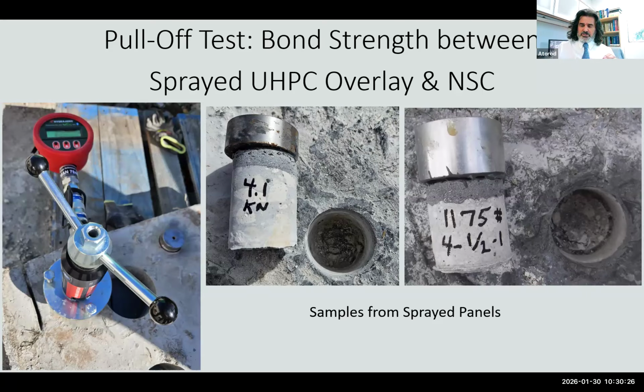If you prepare the surface correctly, and at the time of the spray or cast in place you make sure that the surface is wet, because UHPC doesn't have much water in it. The water-cementitious ratio is 0.18 to 0.2. If you don't keep the surface of the normal strength concrete wet, it's going to soak up all that small amount of water from the UHPC, and then you're going to get shrinkage cracking, things like that. So if you prepare the surface correctly, there is no concern about the bond, which is very good news.